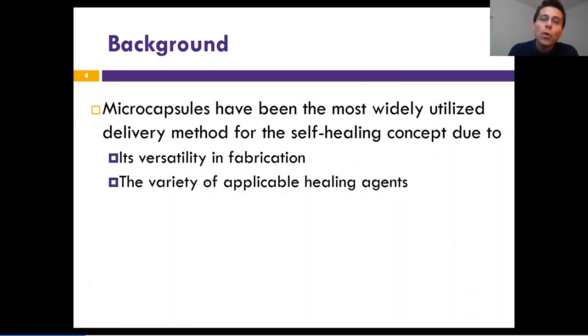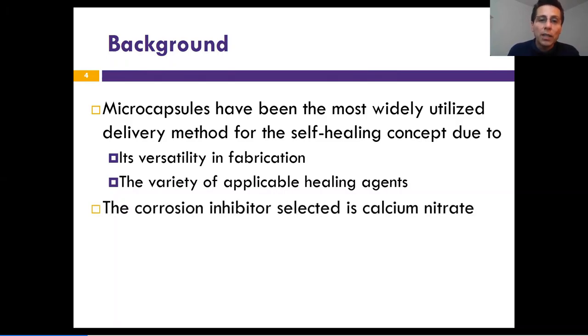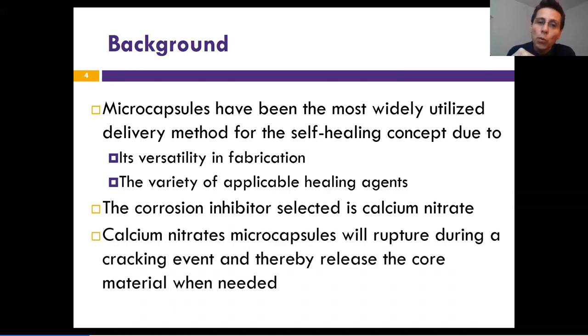These microcapsules have been the most widely utilized delivery method for the self-healing concept. Why? Because it's versatile, and because of the variety of applicable healing agents that we have, we can put many chemicals. Then these chemicals, according to the concrete and the environment, can be used for the self-healing effect. So inhibition is a process where we capture the corrosion precursors in stage one to avoid passing to stage two.